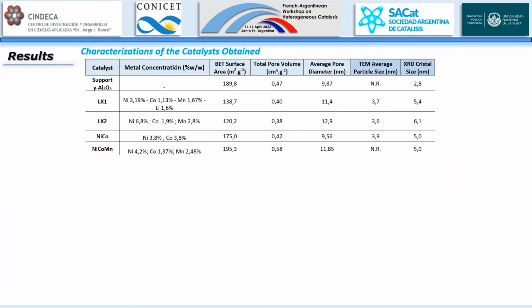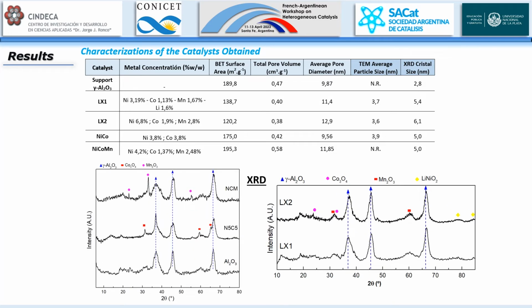This table shows some results of the characterization of the solids prepared by wetness impregnation over gamma alumina support and calcined at 600 degrees. The solids named LX1 and LX2 were impregnated with the leached solution with rising concentration. For comparison, two more catalysts with the same metals were prepared with commercial salts. The X-ray diffraction pattern detected similar phases of manganese and cobalt oxides and didn't detect the nickel oxide phase, which is believed to be well dispersed over the surface due to interactions with other metals present.